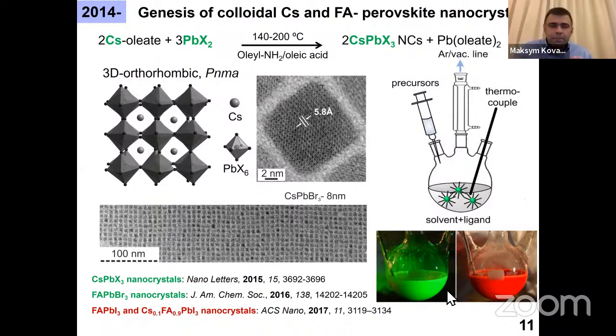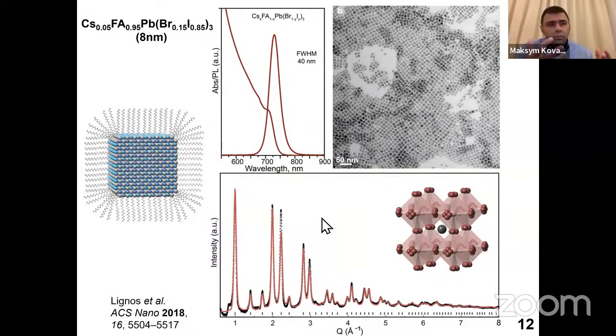And what was super exciting back then, that as you produce them, they emit very bright light. So you don't need to overcoat them with any other semiconductor. As they are bright emitters because apparently their surfaces are relatively benign. They don't introduce mid-gap states. And that is the first example of wide band gap semiconductors, whose surfaces are relatively benign with respect to the electronic behavior. So what was also very exciting is to observe that now you can mix different ions and create multinary perovskite nanocrystals, which is that you can mix A-site, cesium and formamidinium, or halide, so you can have solid solutions. And therefore, you can control the band gap by composition. So you can have phase pure multi-component nanocrystal, which is very difficult to do with chalcogenides, for example.